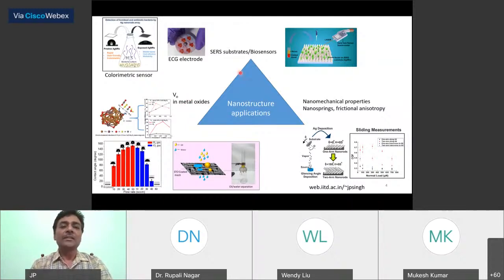And for bio-related things, like yesterday you heard from one of my students, we use silver nanowires and made a colorimetric sensor. Just by the change in the silver nanowire color, one can get an idea about whether the bacteria is live or dead.